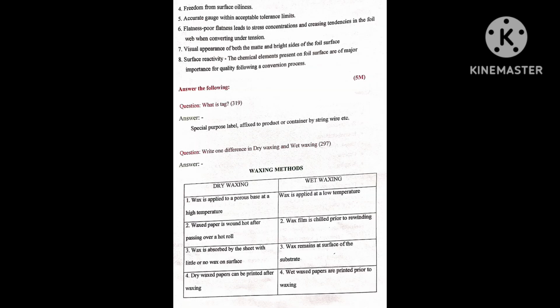Main quality parameters for plain aluminum foil. Mechanical properties: principally ultimate tensile strength, burst strength and elongation. Porosity, both in terms of fine overall porosity and the assessment of large individual holes. Freedom from stiffness, free unwind for foil reels during converting. Freedom from surface oiliness, accurate gauge within acceptable tolerance limit. Flatness, poor flatness leads to stress concentration and creasing tendencies in foil when converting under tension. Visual appearance of both the matte and bright side of the foil, surface reactivity. So here are some qualities of plain aluminum foil.